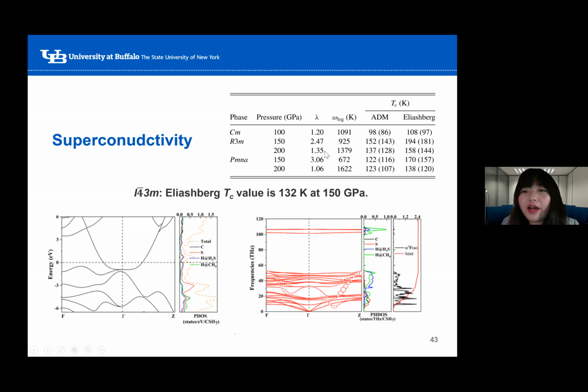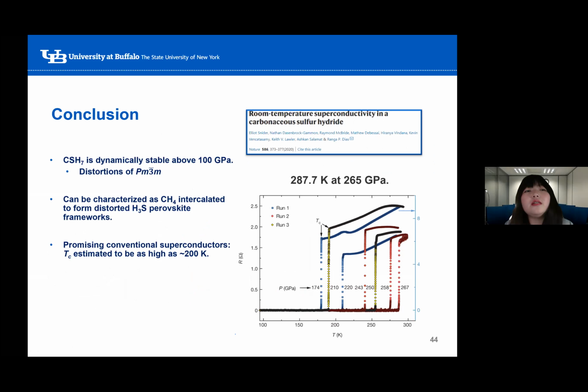Because all of these structures have large lambda, we also calculated their Eliashberg Tc, and that would be this column. So comparing to the Tc we found for Pnma and to the I-43m structure, our Eliashberg Tc at 150 GPa is much higher. So as a conclusion, CSH7 is dynamically stable above 100 GPa, and it can be viewed as a distortion of the Pm-3m perfect perovskites. They can be characterized as methane molecules intercalated to form distorted H3S perovskite frameworks. They are promising conventional superconductors with the highest Tc estimated as approaching 200 Kelvin.